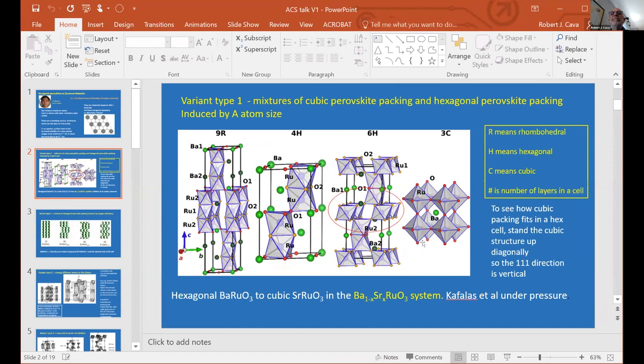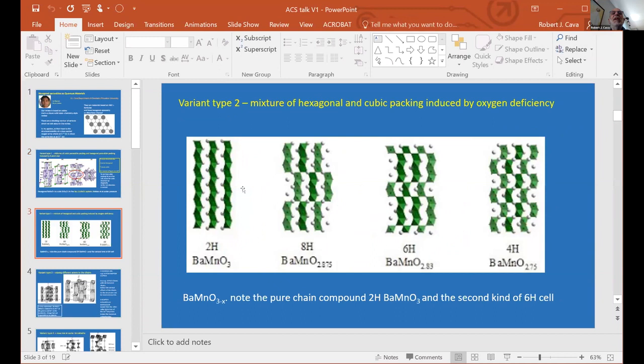So yeah, barium strontium ruthenate is a perfect example of that. And barium ruthenate itself has multiple choices for kinds of structures that it makes. So it's pretty cool. And then if we want to start looking at different variations of hexagonal perovskites, which is what our review is about, you can look at barium manganate, which just has a chain, BaMnO3. You could take some oxygen out and start disrupting the chains. And you can change it to just trimers, tetramers plus dimers, and only dimers by changing the oxygen content. So, you know, it's not so simple.